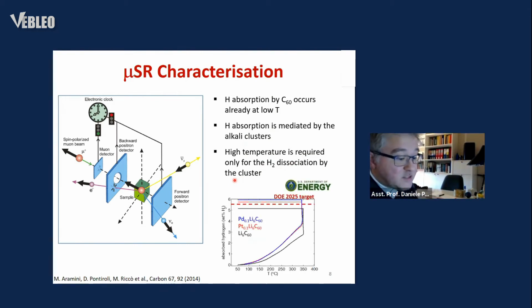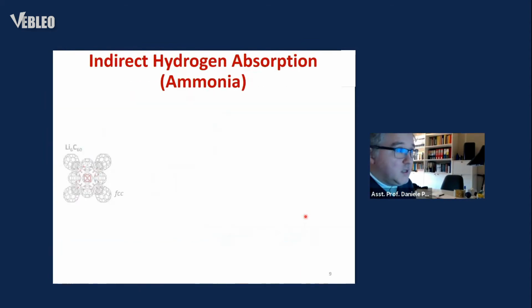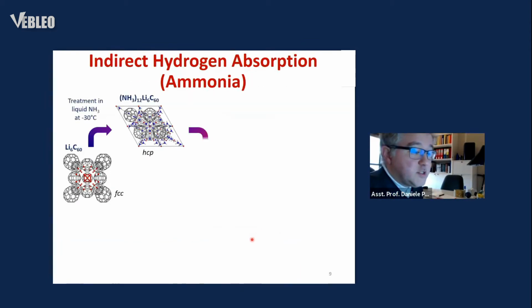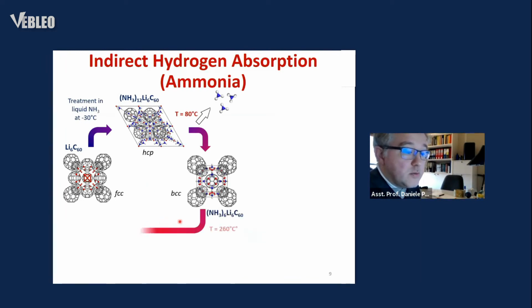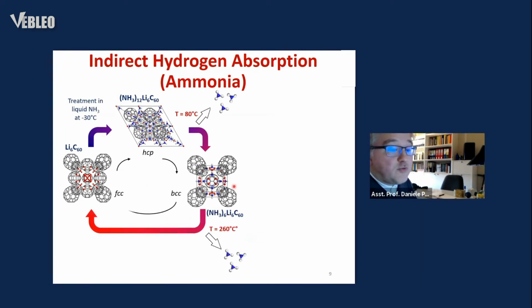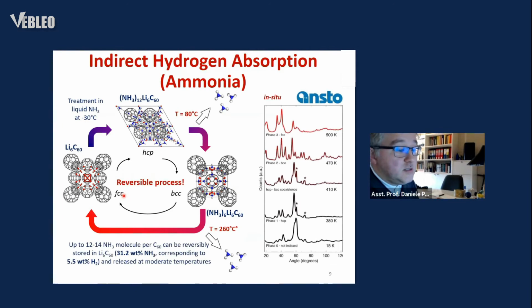And in fact, in this case, we managed to further increase and optimize the hydrogenation of the materials, meeting the DOE target. Let me conclude this part by showing you that a relevant amount of reversible hydrogen in these systems can also be obtained indirectly by the absorption and desorption of a nitrogen carrier, which is ammonia.